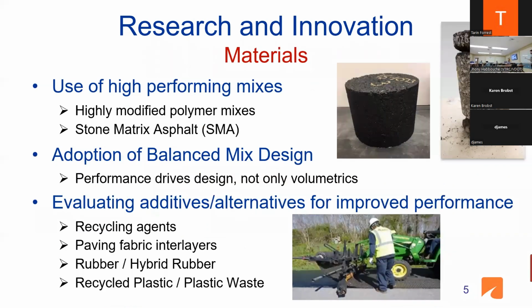When we talk in terms of materials, some of you may have heard of some of the initiatives that we worked on. For example, the highly modified polymer mixes. And usually this is typically used majorly in Northern Virginia, Richmond, and Hampton Roads. The stone matrix asphalt, that's a typical mix that VDOT adopts or uses throughout the entire Commonwealth. Recently, we started shifting towards the full implementation or adoption of the balanced mix design. That's when we do our mix design not only based on recipe, but also based on performance. And we're trying to improve the performance of the mix to be placed on all the roads. And then also we use that framework to evaluate additives and other alternatives like the use of rejuvenators, recycling agents, other stuff like rubber or hybrid rubber, and recycled plastic and plastic waste.